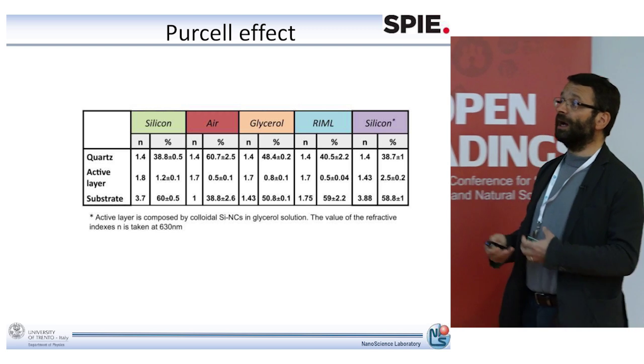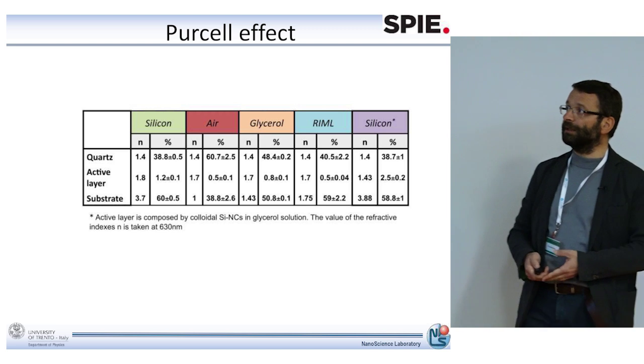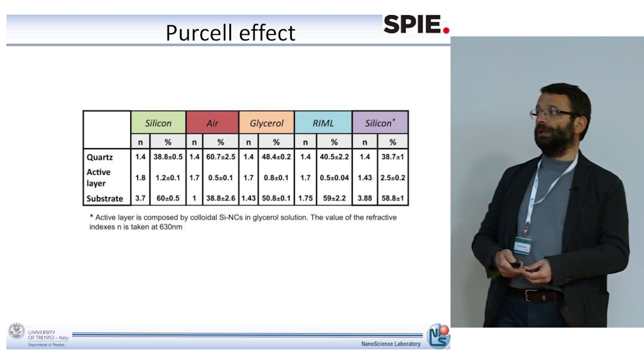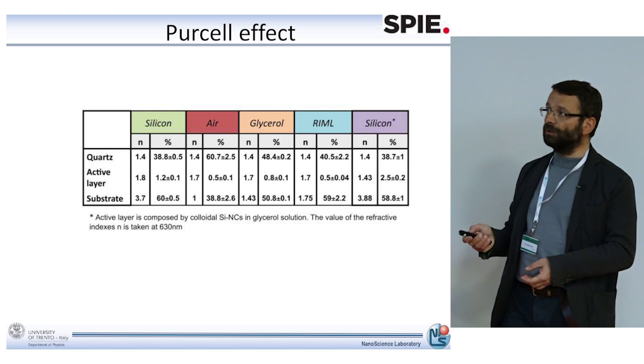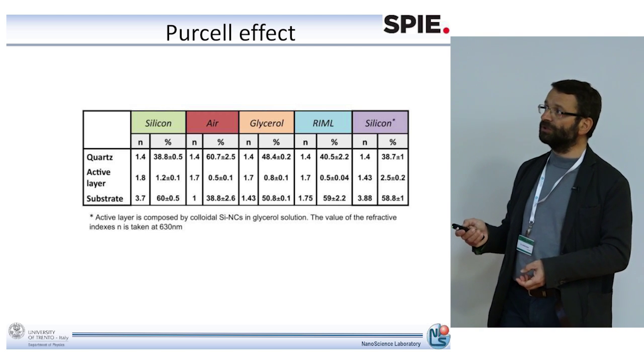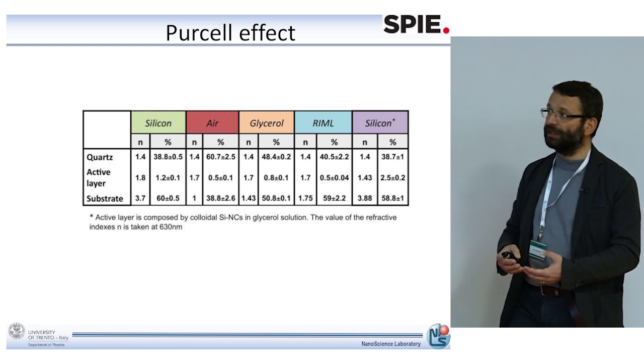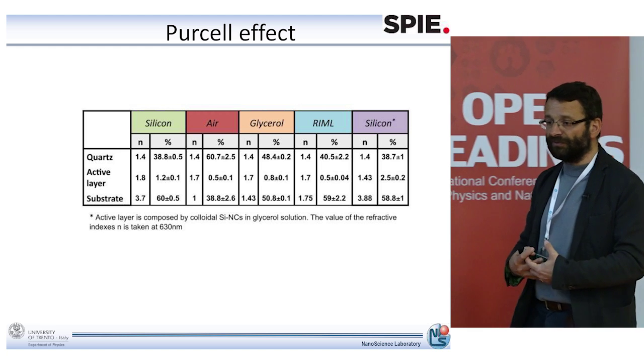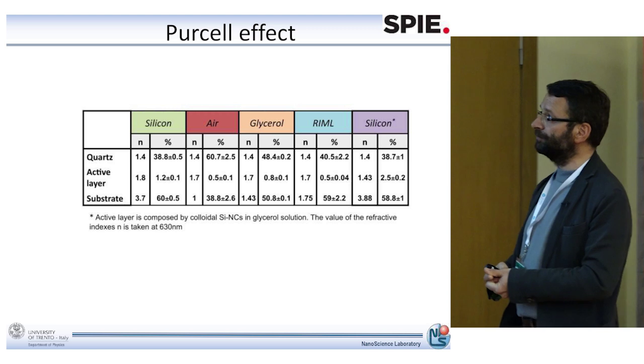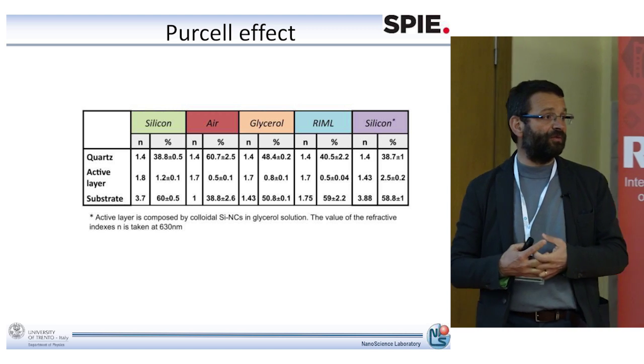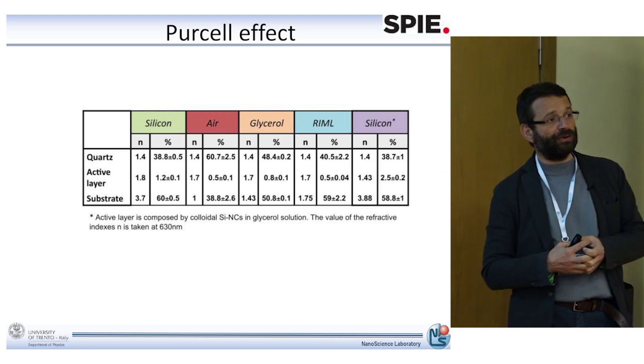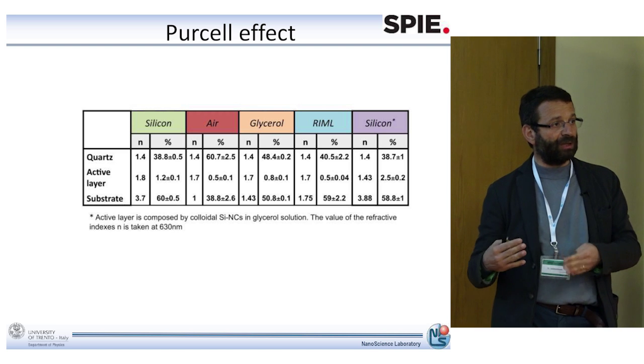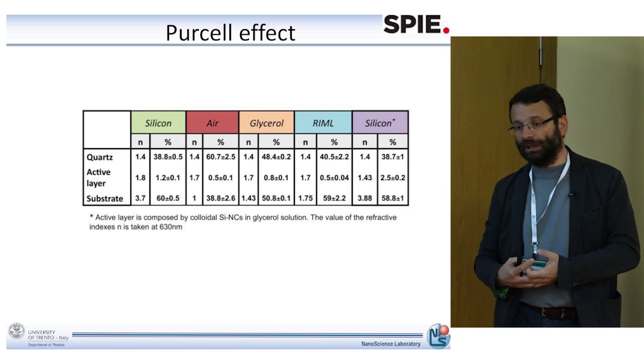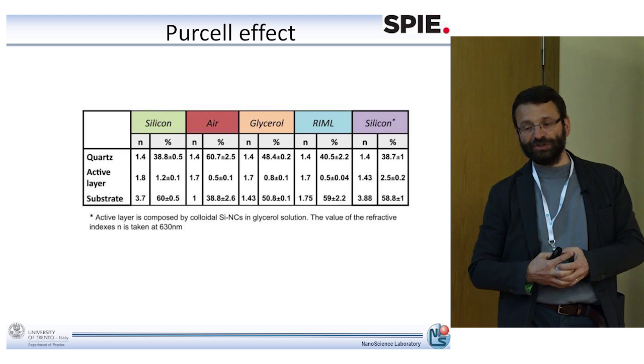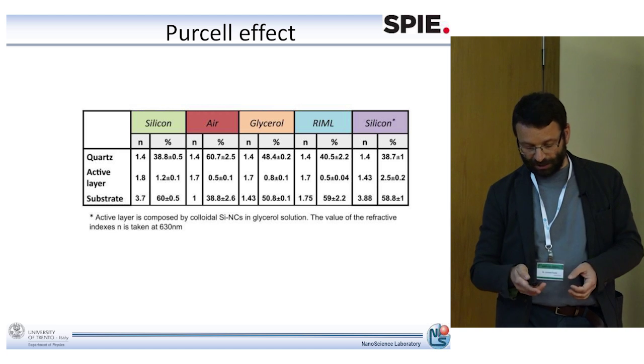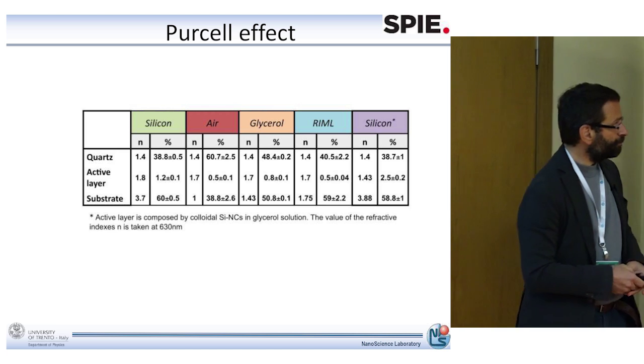And indeed, if now you compare the experimental results with what we have observed, you indeed see that most of the light is emitted into the silicon because of the high refractive index of silicon. So here is an example of how, by using silicon nanocrystals, it is possible to get a 1% conversion efficiency improvement in a commercial silicon cell.